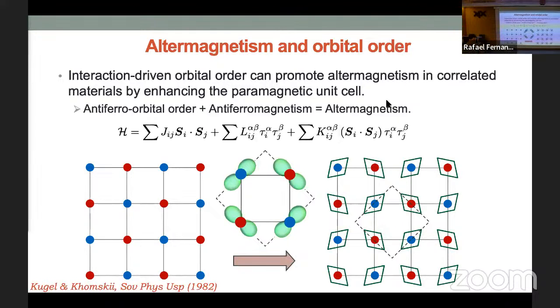And this is actually part of a solution of a wider class of systems, and they're described by this effective model called the Kugel-Khomskii model, where you have spins, and you also have pseudospins describing these orbital degrees of freedom. Okay, and if both of them are oriented in an antiferro kind of way, what I mean is both want to be antiferromagnetic and antiferro orbital order, which means that the scale here generally has to be negative, you would get something like that. Okay?